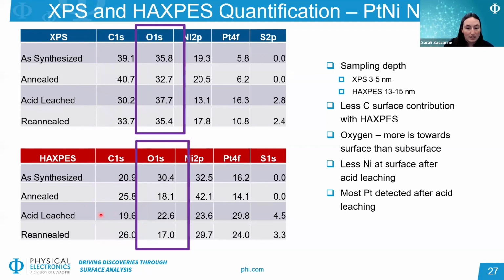With the oxygen data, we see again that there is more towards the sample surface, which correlates with some of the spectral overlays we saw in the previous slide. And we still see some differences with the post-processing steps.